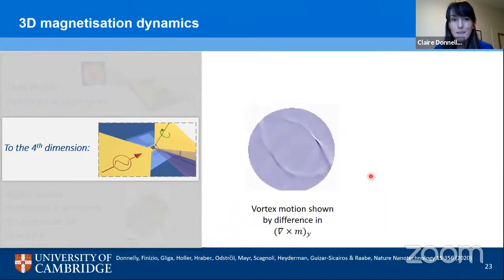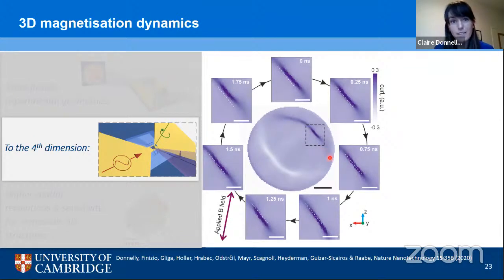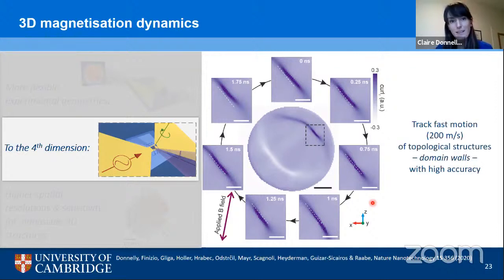And with this four-dimensional information, we can directly look at the dynamics in 3D. So what we can first of all do is go to our vortices in the bottom of our disk. And what I'm showing you here is a difference image where this purple line is our vortex, the core of our vortex domain wall. And it's oscillating, as you can see, around this white reference line. We can track the position of our vortex core with high accuracy and determine actually that it's moving at approximately 200 meters per second over the 2 nanosecond period of the excitation, demonstrating essentially that we can track topological structures buried within the bulk of a system with high accuracy.